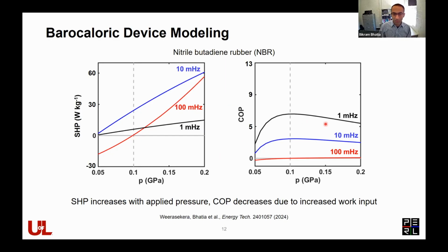For the COP, the results are quite interesting. If you look at it as a function of pressure, you see that the COP initially increases, and that's because, again, you apply more pressure, you have a larger delta T or entropy change. That increases the numerator of the COP equation. And as you keep on applying more and more pressure, the work input increases exponentially with pressure, which causes the COP to drop after a certain point. So there is really an optimal pressure that you need to apply to maximize the COP of a heat pump.